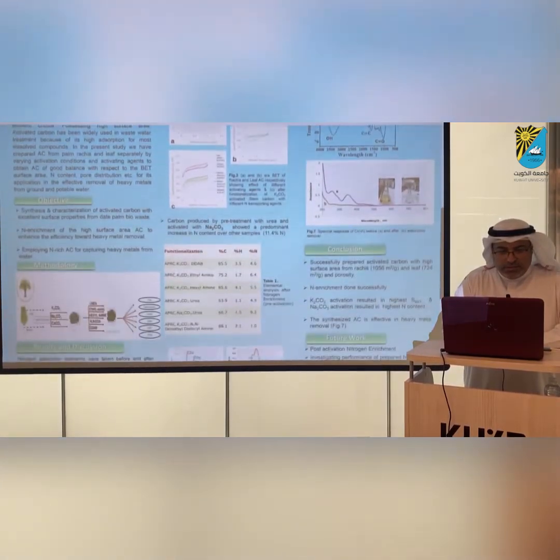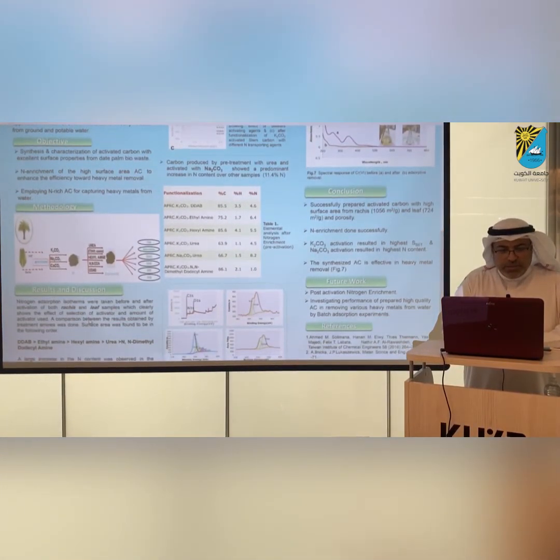If you can see here, this will summarize the experimental procedure. We start with the bioproduct, the plant. We have to do pyrolysis. We put it in a furnace in order to burn it under a nitrogen environment. It has to be under nitrogen, and the oxygen should not be available at all. Otherwise, all the carbon will be converted to carbon dioxide and carbon monoxide and evaporate. So we have to make sure the nitrogen used is a very highly pure gas.